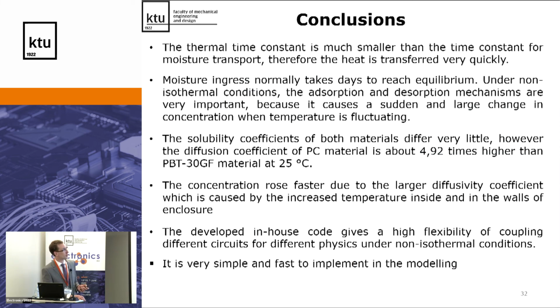Of course, the thermal time constant is much smaller than the time constant of moisture transport. Therefore, heat is transferred quickly, and then the moisture ingress may take a very long time. And the adsorption and desorption mechanisms are very important because they cause a sudden and large change in the concentration. And here we can have big problems with moisture-related issues like corrosion, because when we have a sudden temperature change, the concentration really changes due to the adsorption and desorption mechanism.